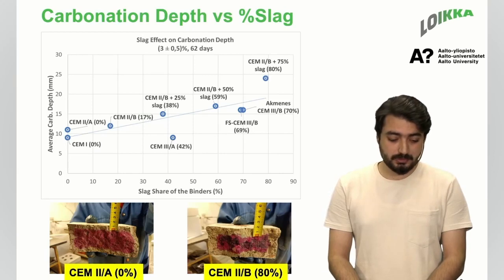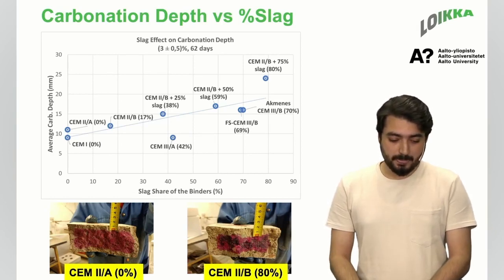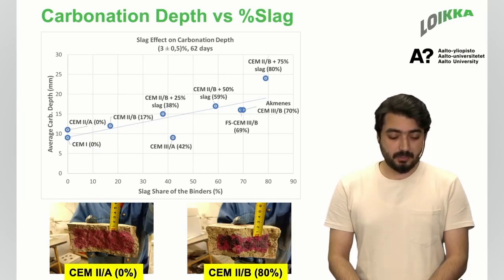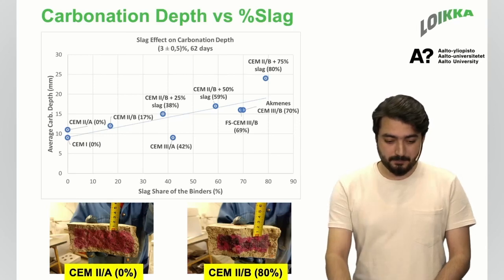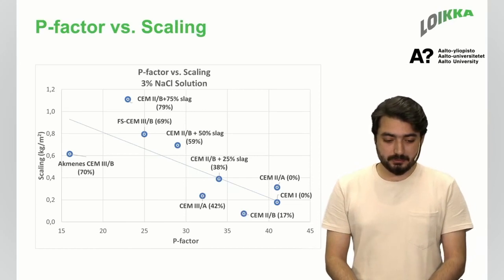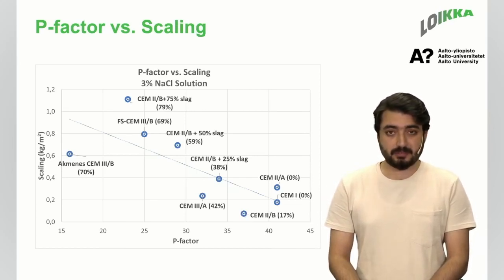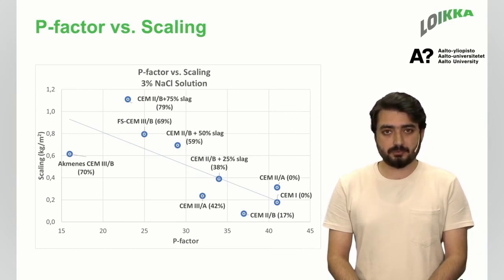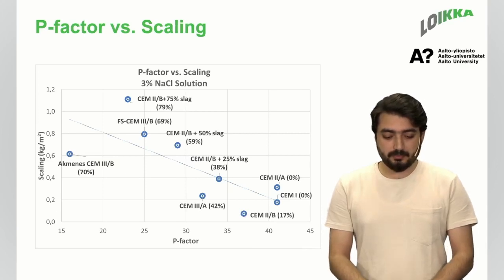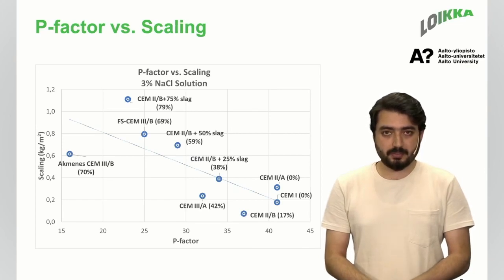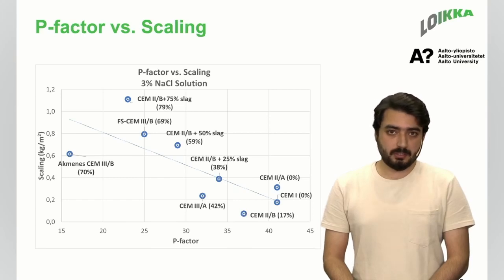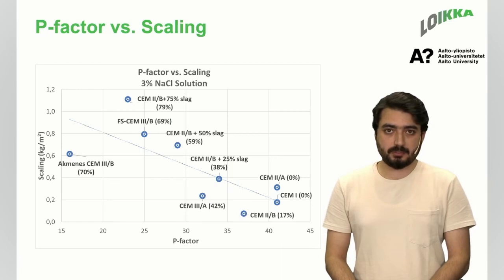You can see the 2 different pictures of the carbonation. The uncolored, non-pink borders that the samples have are where we can measure how much the carbonation depth was. With 0% slag, it clearly shows a lesser carbonation depth than with 80% slag. Another factor that we examined during our project was the P factor, which is mainly used by the Finnish Transportation Agency for studying the service life of the structure. Here we can see that if the slag is lower, we have a higher P factor, which shows that the concrete material is more resistant to freeze and thaw, and it will have a higher service life.